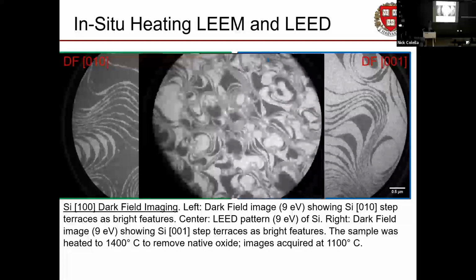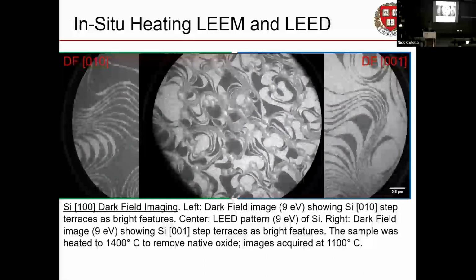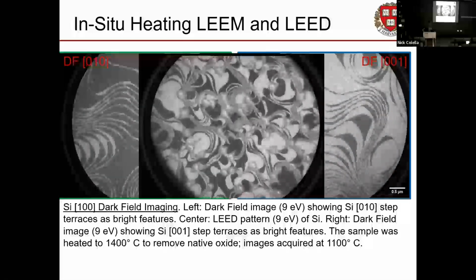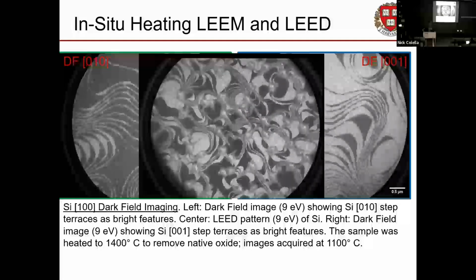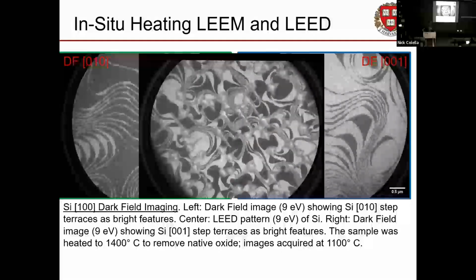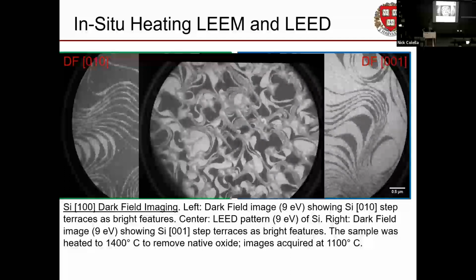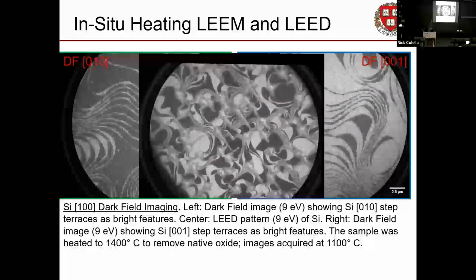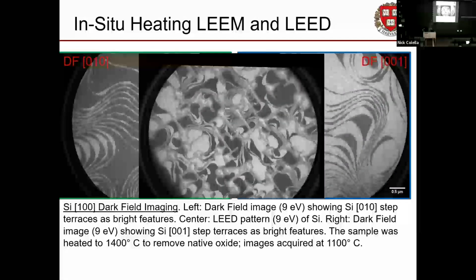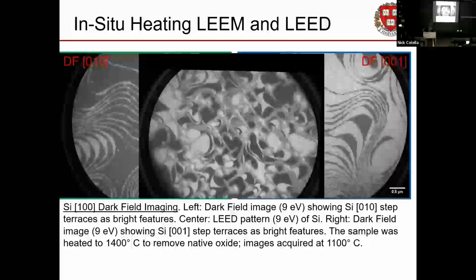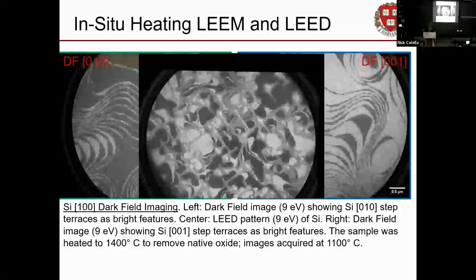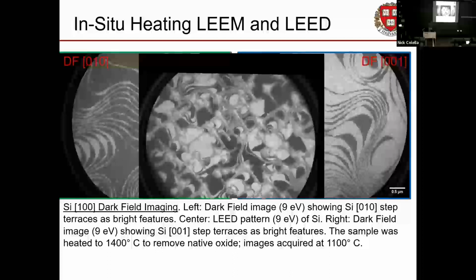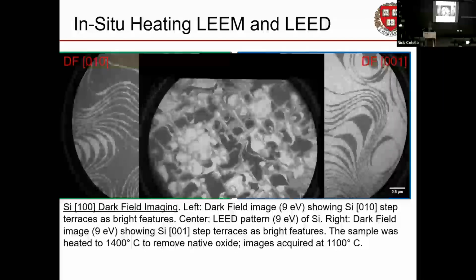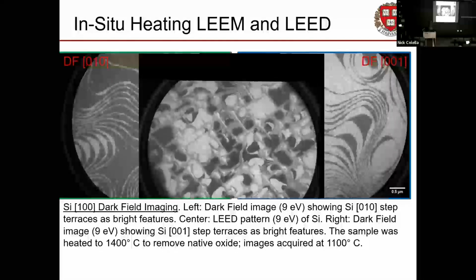But what if we heat it up? And if we heat it up, we get to watch these atomic planes grow. And these are atoms actually migrating around on the surface of the silicon, trying to flatten the little hills out. You can imagine this sort of like a geographical topography plot. And since it's warm, it wants to be flat. It doesn't want to have hills and bumps. Everybody wants to have all their bonds satisfied. So everybody's just going to move around.